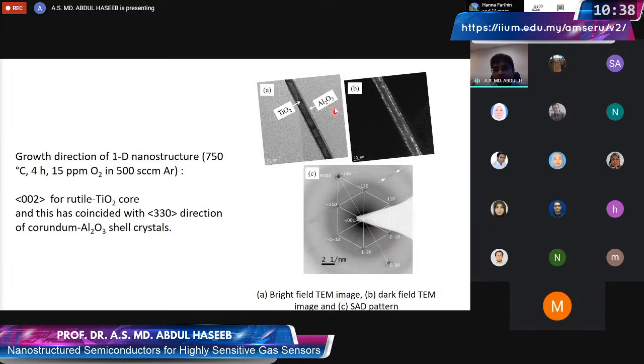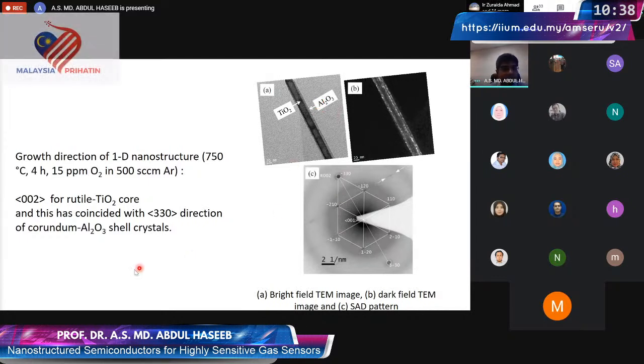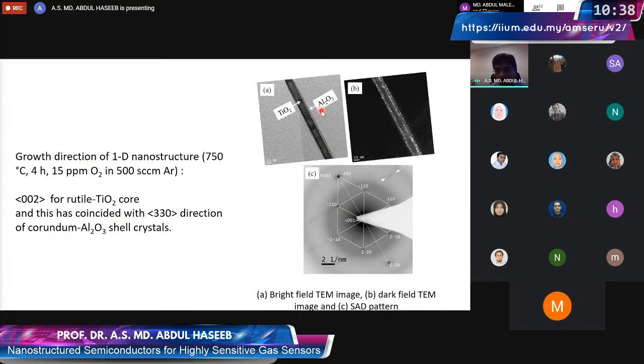We also notice that the aluminum oxides are very small crystals in size. And we determined the growth direction as well, which is the 002 direction for rutile. So this is the growth direction, which is 002 in this particular case. And this is the same, or more or less similar, for other nanowires as well.